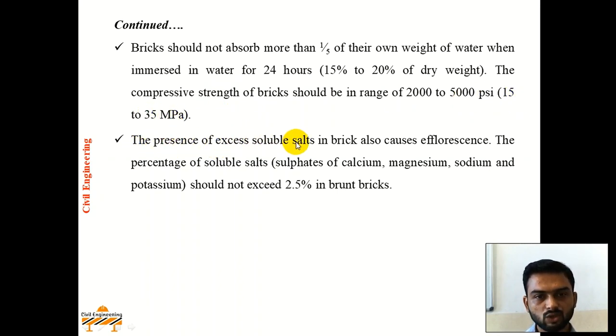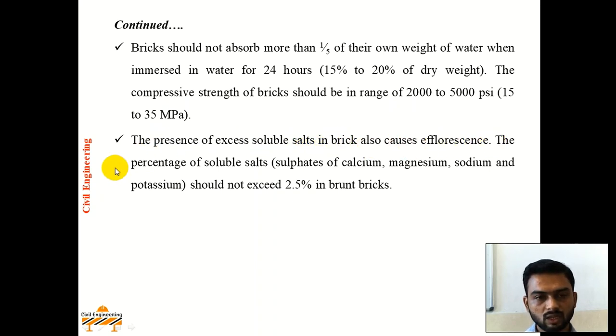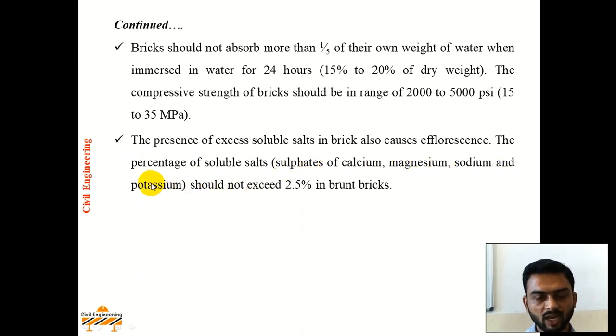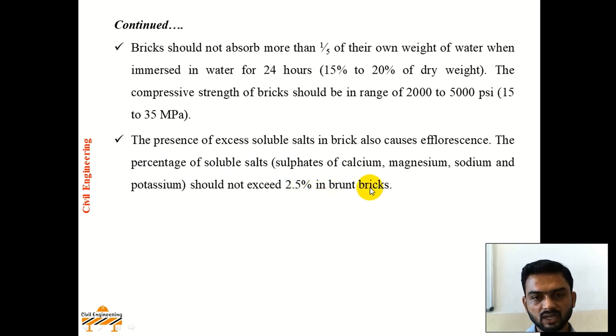The presence of excess soluble salts in the brick causes efflorescence. The percentage of soluble salts, i.e. sulphates of calcium, magnesium, sodium, and potassium, should not exceed 2.5% in the burned bricks.